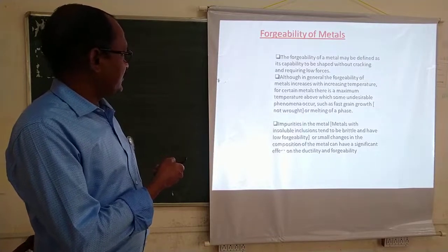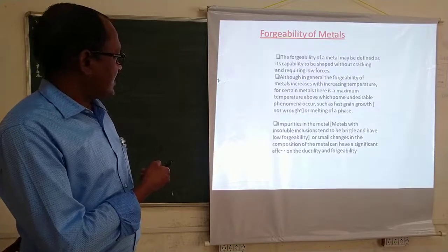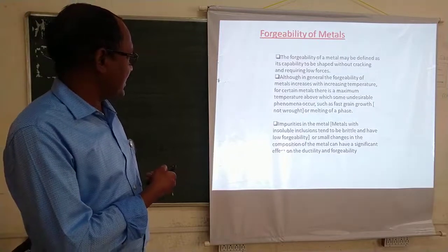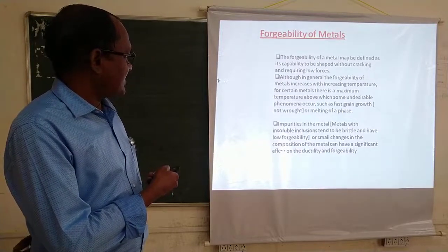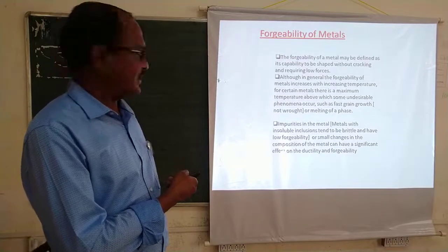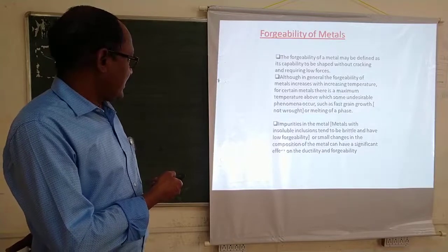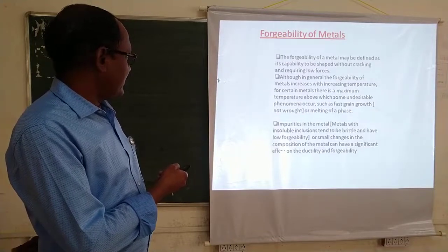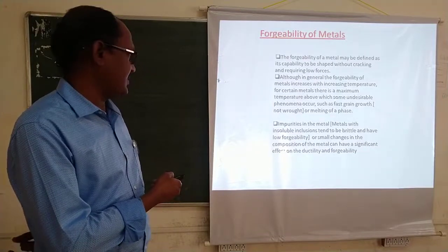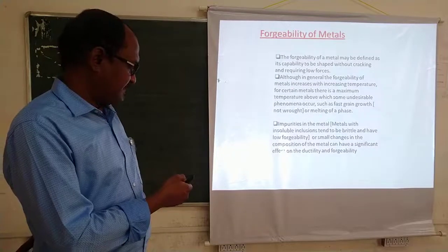Although in general the forgeability of a metal increases with increasing temperature, for certain metals there is a maximum temperature above which some undesirable phenomena occur, such as fast grain growth or melting of a phase. Metals with impurities and insoluble inclusions tend to be brittle and have low forgeability. Means a brittle material you are not able to forge properly.